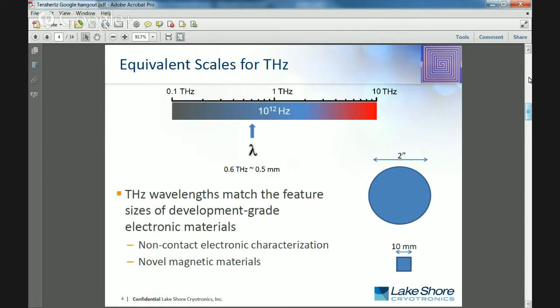But while there are other solutions out there that allow this non-contact evaluation of free carrier motion in materials, the wavelength is actually much longer than what we find in the terahertz range. And so typically you need a sample that's 2 inches in diameter. What we've found is that for a lot of research-grade materials, the growth is done on much, much smaller substrates, typically a 10 by 10 millimeter substrate.